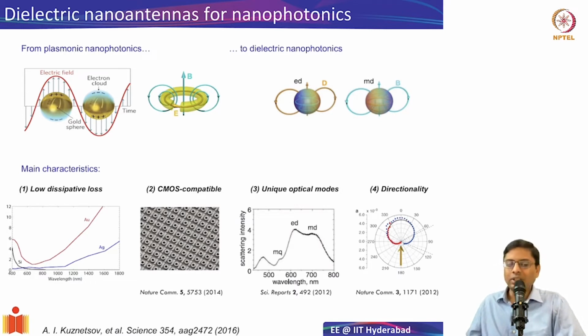All right. So I already mentioned loss. We have these traditional plasmonic resonances. So you excite the plasmonic resonance, and you can also have split ring kind of structures wherein there's a circulating electric field, and that causes a magnetic field. And I mentioned that these structures suffer from loss. So this is an example here. Basically, this is the loss for gold and silver plotted with respect to wavelength. And you see that the silicon loss is quite low. You might say, oh, silicon should actually have loss up to 1100 nanometers. Why is the loss low? Well, it turns out that for silicon, you can also make amorphous silicon. If you have amorphous silicon, it has an optical band gap of about 700 nanometers. Anything above that, it's lossless. All right.